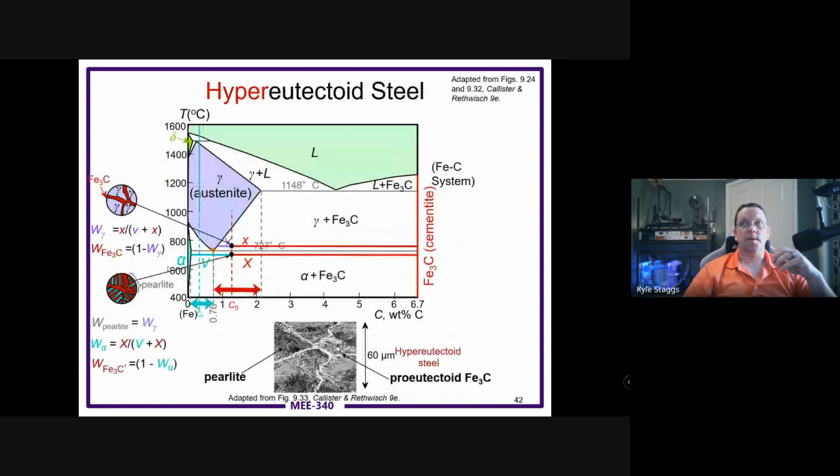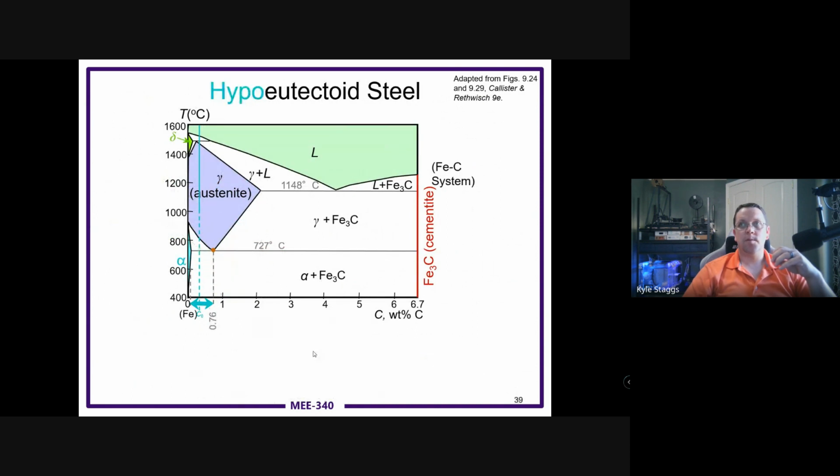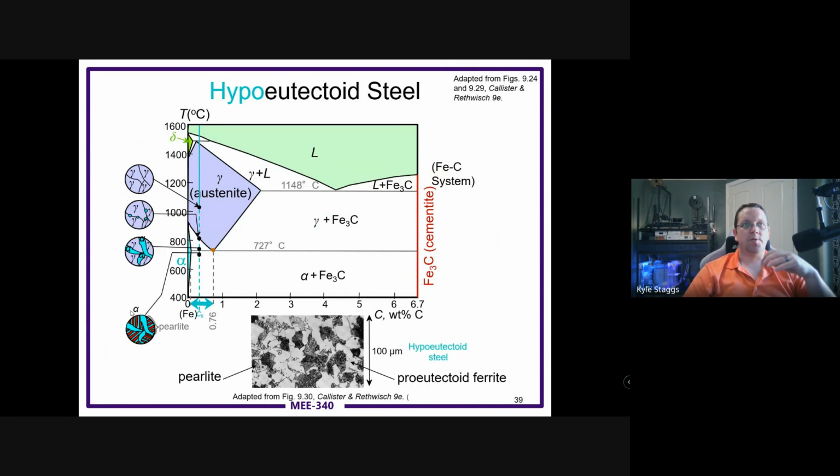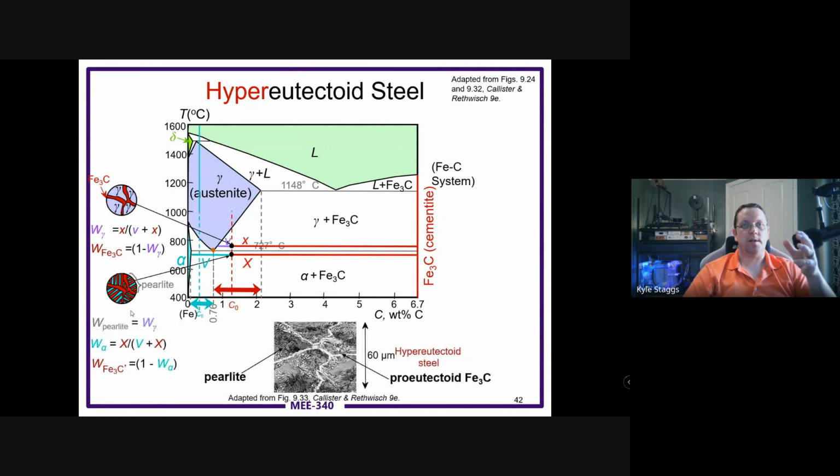You guys have seen it, but let's look again quickly at an image. It's a little better represented here. Think of these particular pearlite crystals as having these cementite bands. Think of it almost like a deck of cards or a phone book, something with a lot of layers stacked in the same direction. You can bend it, but trying to tear or shear that is very, very difficult. When all of these layers are present, you have a lot of resistance to movement. Bending is reasonable for something like that, but the actual structure of this grain is such that it doesn't really want to compress as readily, whereas the natural ferrite itself, those grains are much more able to move around and slip. There are other factors like the kinds of crystalline boundaries and all of those sorts of things, but that's why these are important and why the grain nucleation is important on these.